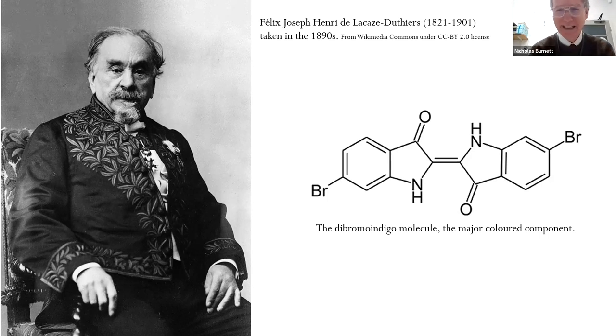In his paper presented to the Royal Society, Lacaze-Duthiers states that the color change is accompanied by the development of a most penetrating and fetid odor analogous to that of garlic oil. According to color lexica, the dye shellfish purple is composed of a mixture of indigo dyes — indigo, monobromo indigo, and dibromo indigo — with a small amount of corresponding indirubins. Dibromo indigo's molecular structure is identical to indigo but with two bromine atoms, one on each end, and can vary from 77 to 91 percent of the dye depending upon the species of mollusk.